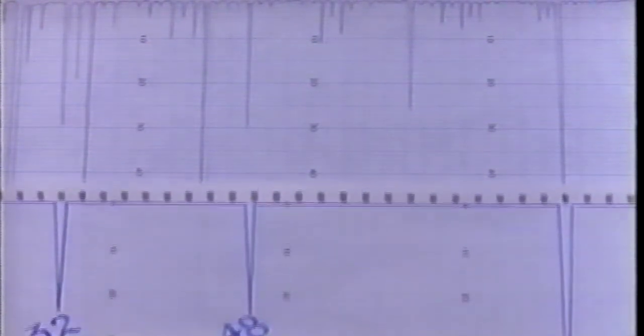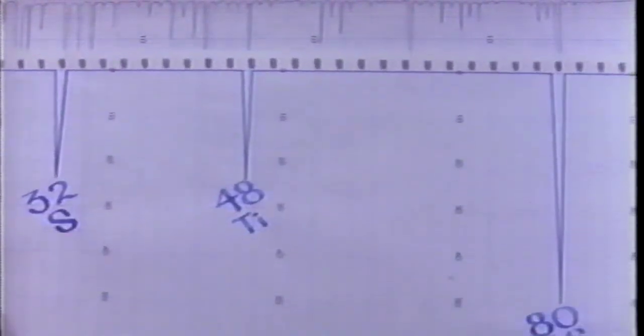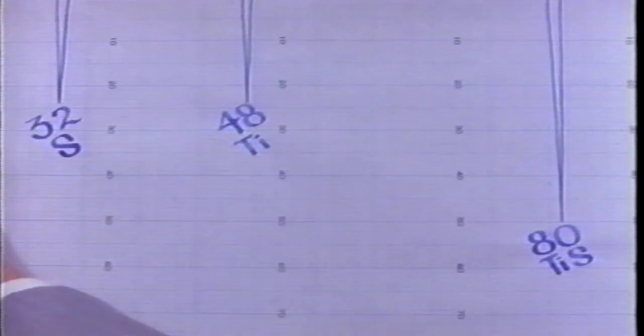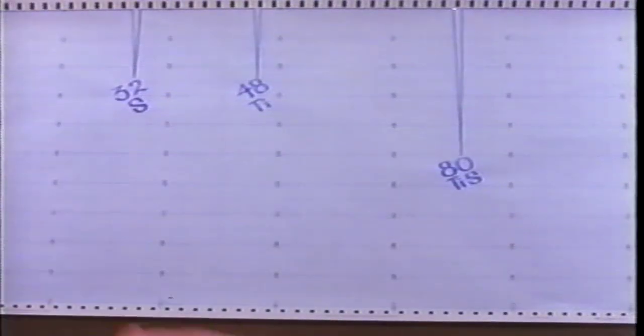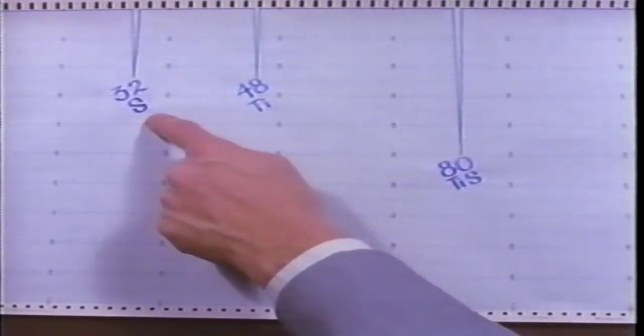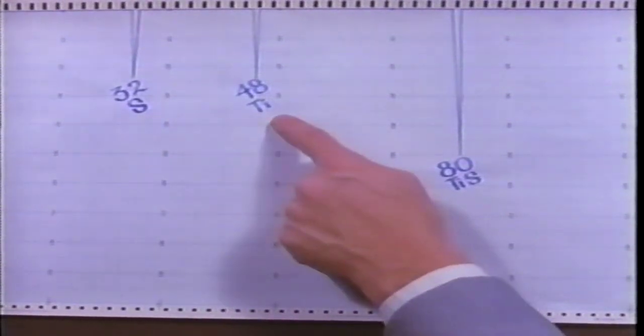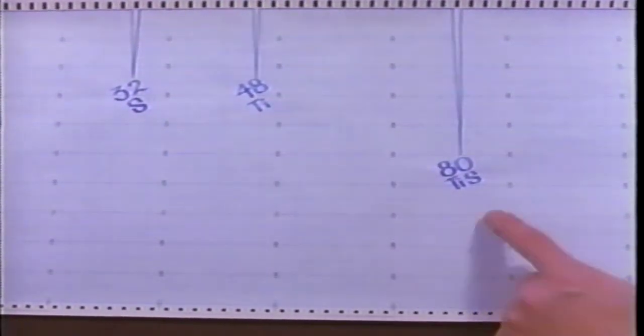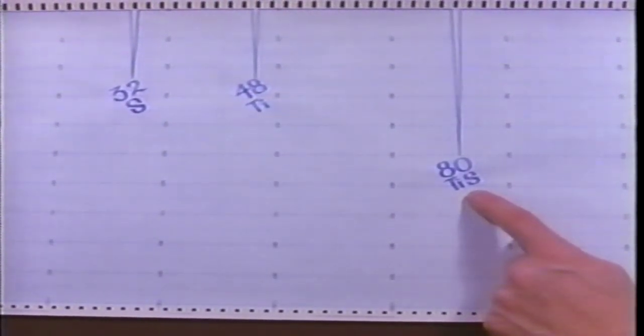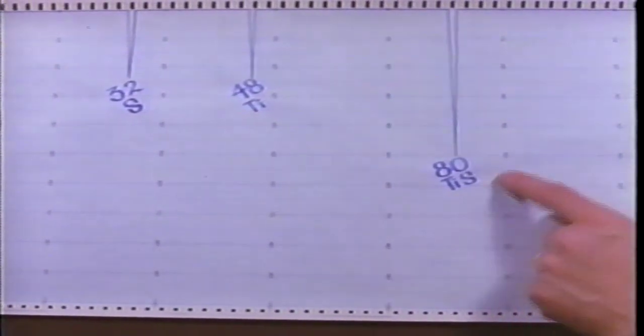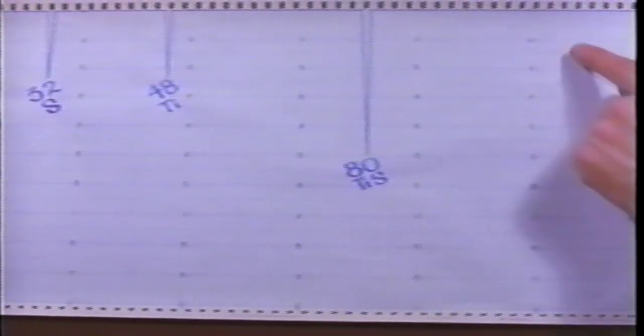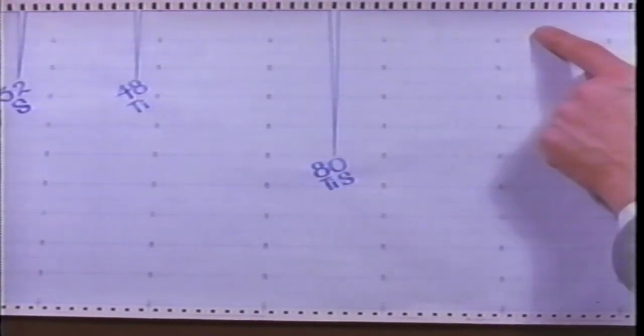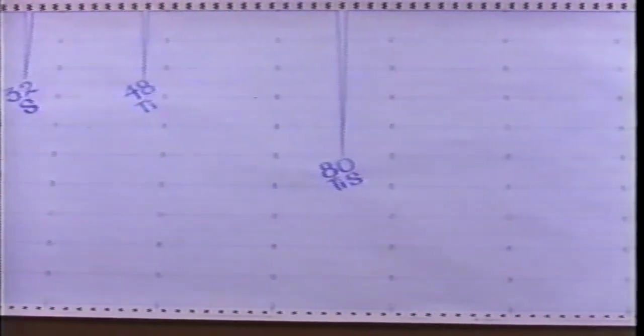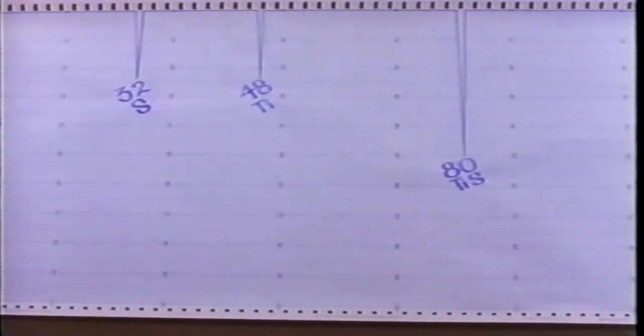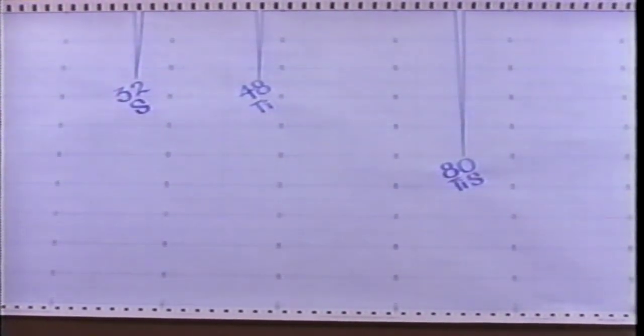We have eliminated all the background peaks, and also those arising from the different isotopes of titanium and sulfur. The peak at mass 32 comes from sulfur. The peak at mass 48 comes from titanium atoms, and at mass 80 from TiS molecules. If TiS2 molecules were formed, they would appear at mass 112, but we found none. As you can tell, TiS is a principal constituent of the vapor at this particular temperature.